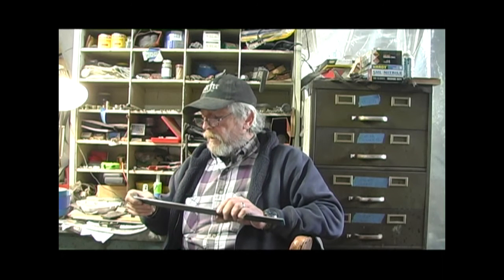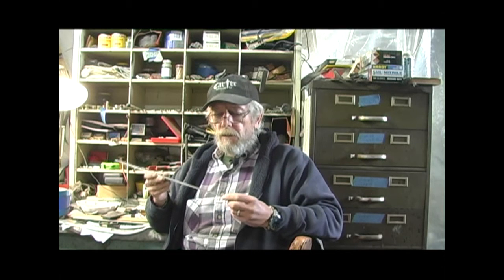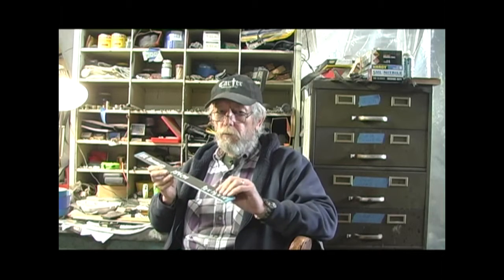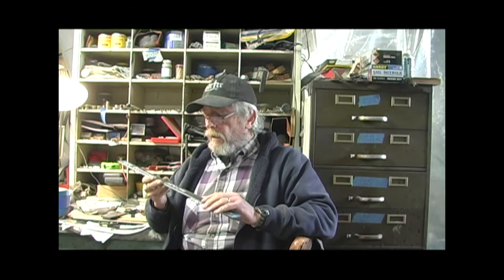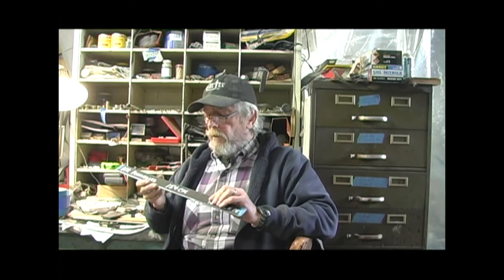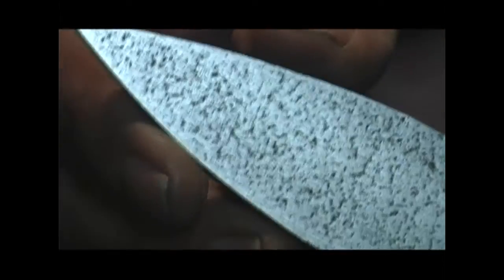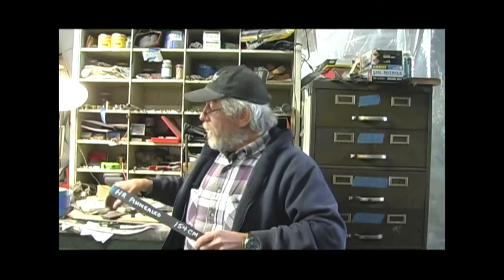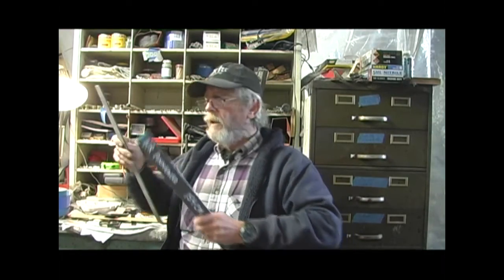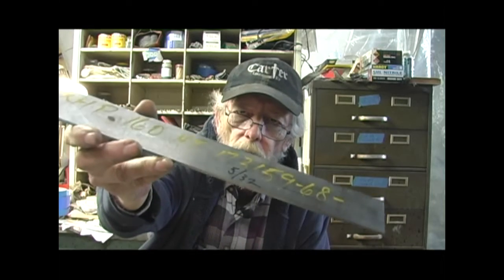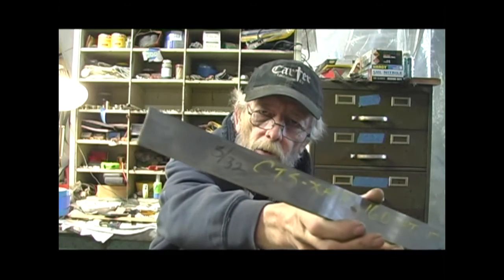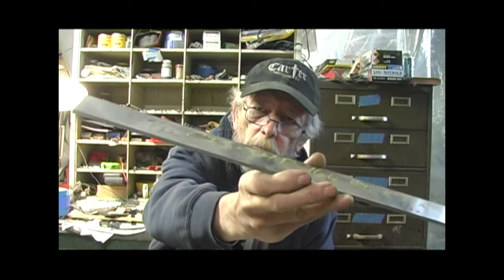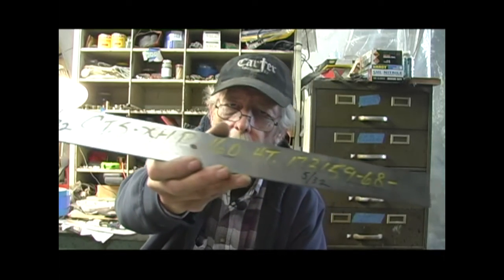And also, at the mills, they put it through a pickling process, where they put it in an acid bath to remove the mill scale that forms on the surface of the steel. And the pickling leaves kind of a pitted finish on the steel that often has to be ground out. Now you can also buy your steel in precision ground bars where that pitting has already been ground out. It gives you a very smooth, clean surface to start with.